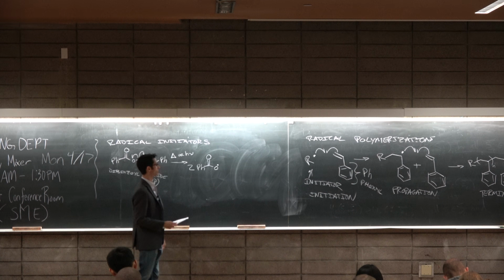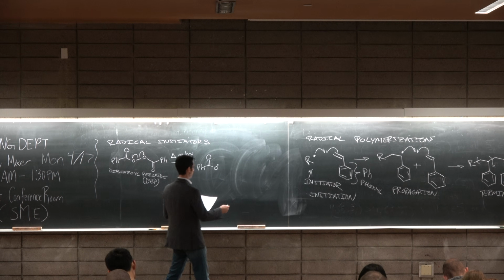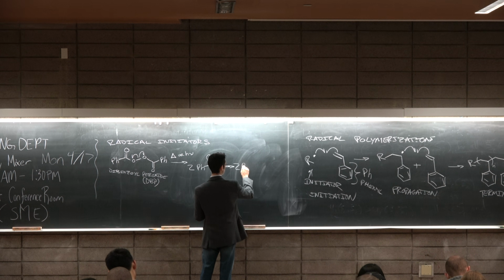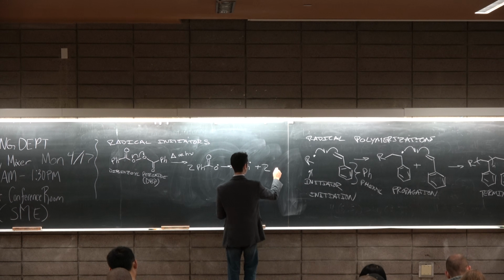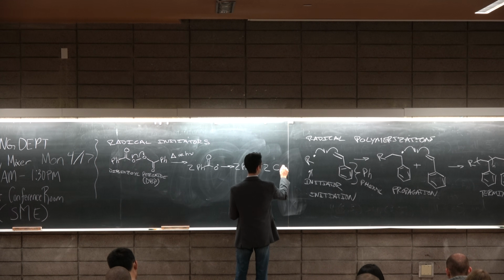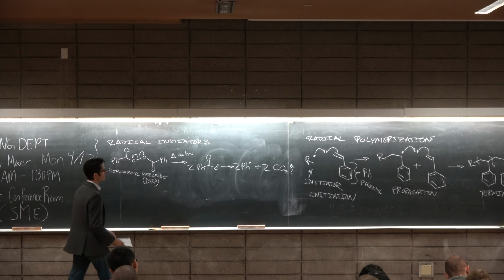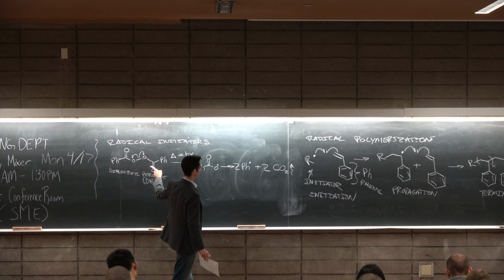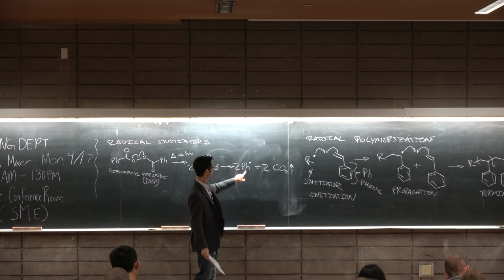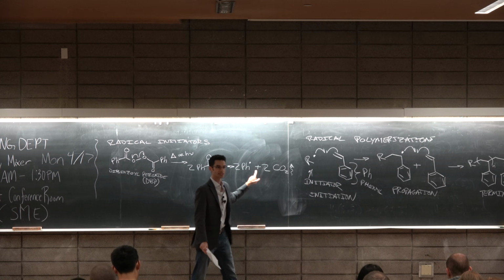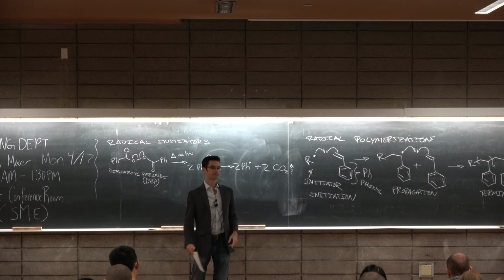So we have two of these benzoyl radicals, which decompose automatically further to two phenyl radicals plus two carbon dioxide molecules, which bubble off. And then in this case, you get two radicals. The Ph is R over here. So this is what initiates the reaction. Yep. Okay.